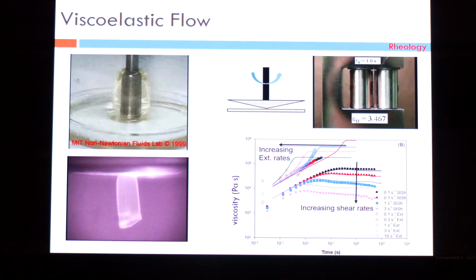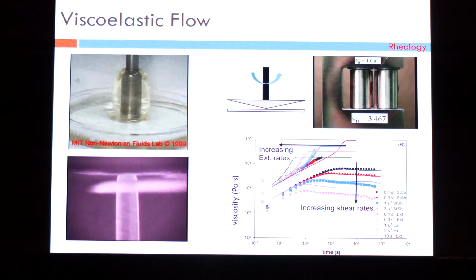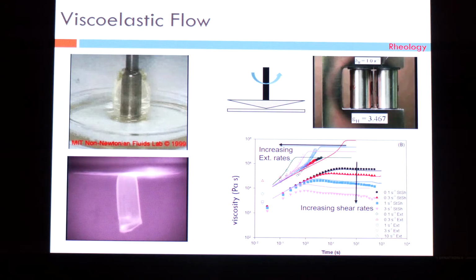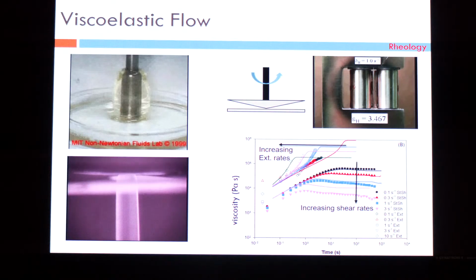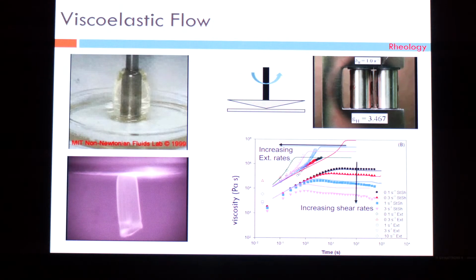And so as you see, with increasing shear rates, the viscosity actually goes down. It of course rises, reaches a plateau, which is a steady state viscosity, and that steady state viscosity decreases as you increase the rate of rotation. The faster you rotate, the higher is the shear that you are imposing on the liquid, the lower is the viscosity. So these materials are what we call shear thinning liquids.